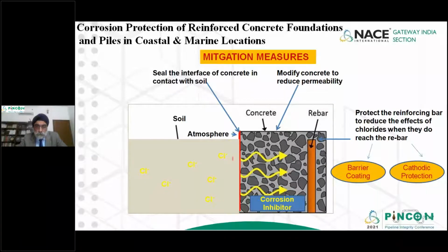So this is a rebar cast in concrete. The distance between the rebar and the outer surface of the concrete is called the concrete cover, and it is embedded in an atmosphere where chloride ions are floating around, which can either be soil or an outside atmosphere. So how do you protect the rebar? Either you do a coating, or you apply cathodic protection, or you do a combination of both. So that's one strategy. The other strategy is to apply a coating on the concrete surface between the concrete surface and the soil. So this is another strategy.